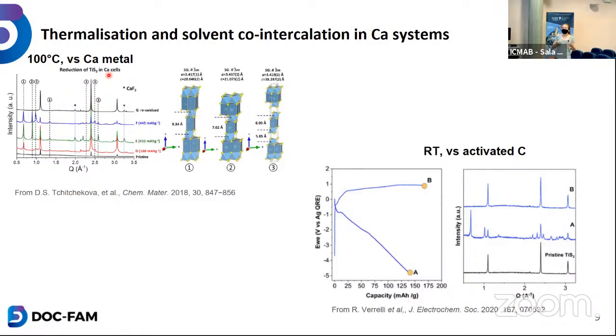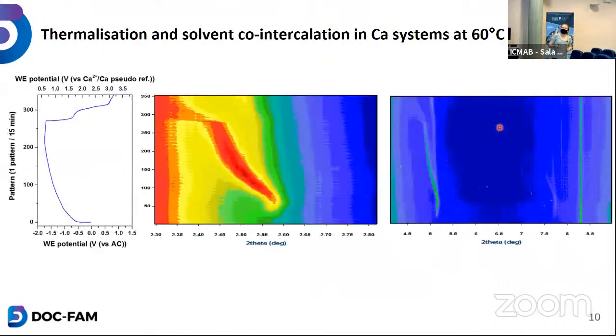So to optimize the calcium battery, we replaced metallic calcium with activated carbon. And this time you can operate with different electrolytes and you can also operate at room temperature. So it's a great progress. Here, we tried to do it at moderate temperature. So we used our thermalized cell at 60 degrees, and we used an activated carbon versus titanium disulfide cell. And as you can see, we can find again these 3 co-intercalation peaks, but you also have an additional peak.